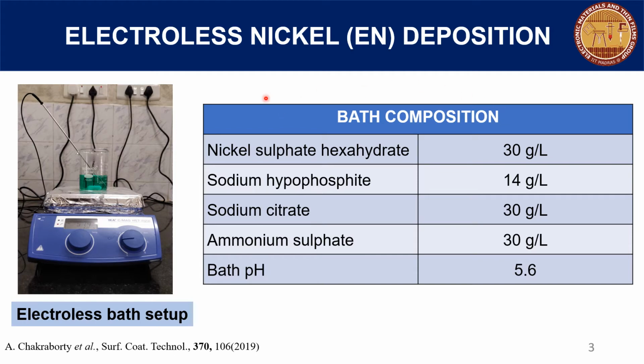A typical electroless nickel bath consists of a source of nickel ions, a reducing agent, a complexing agent, and a bath stabilizer. In this work, nickel sulfate is used as the source of nickel ions and sodium hypophosphite is the reducing agent, and the natural pH of the bath is 5.6.